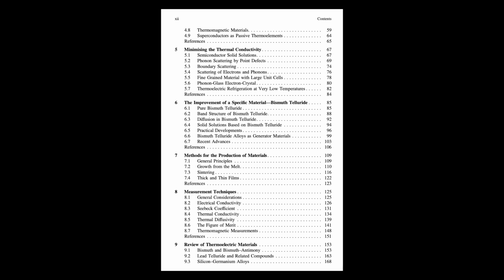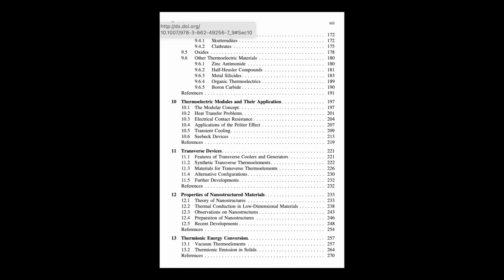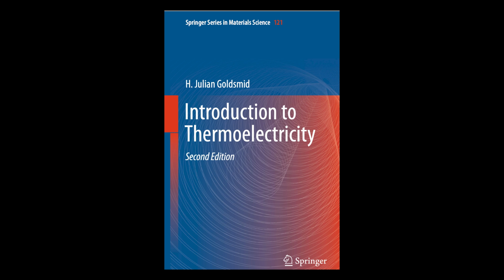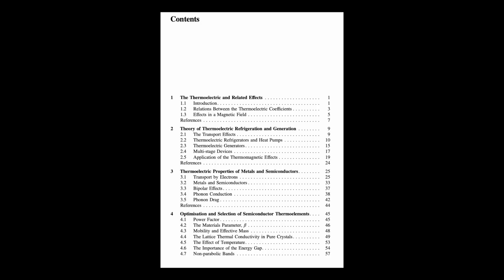Clever. Okay, so moving beyond the basics, how do we judge how good a material or a pair is? The figure of merit came up. The figure of merit. Yes, very crucial. When you build a device, say a cooler, from a P-type and an N-type material, a thermocouple, its figure of merit, Z for the pair, tells you how efficient it can be. Essentially, you want to minimize the combined thermal and electrical resistance of the two legs of the thermocouple. And when you optimize that mathematically, you get this Z value that depends on the Seebeck coefficients and thermal conductivities of both P-type and N-type materials.